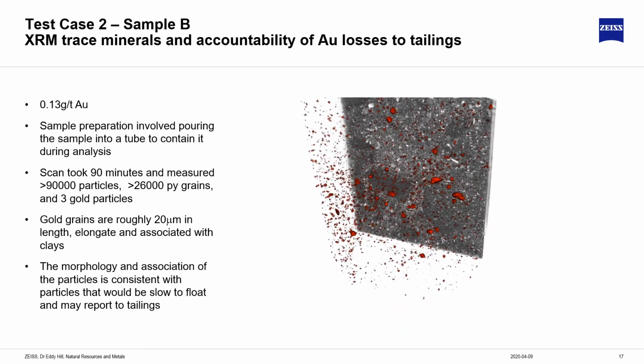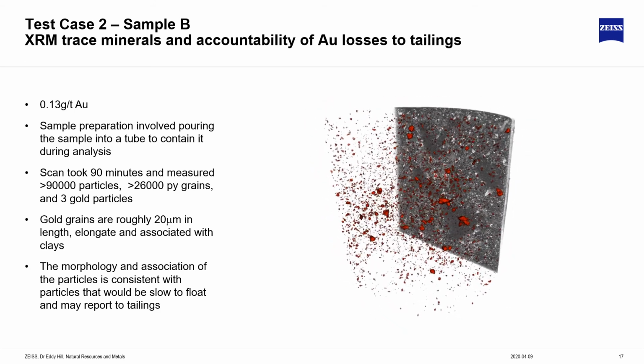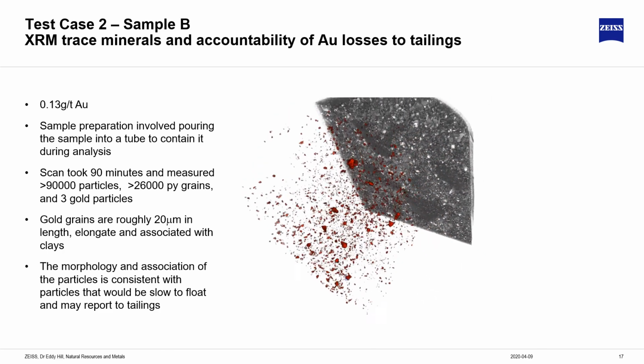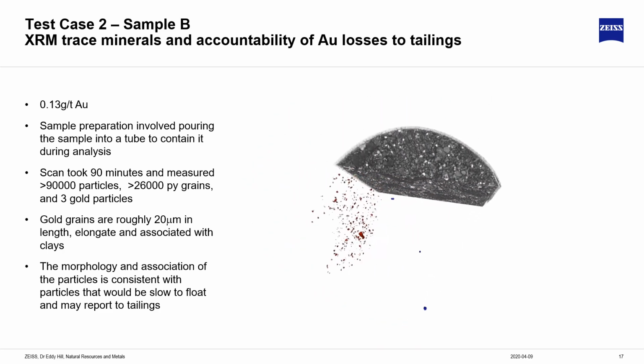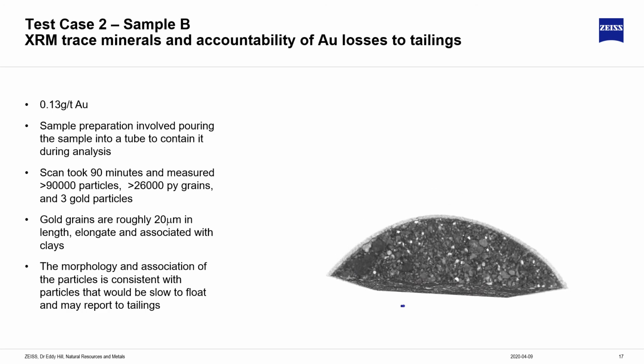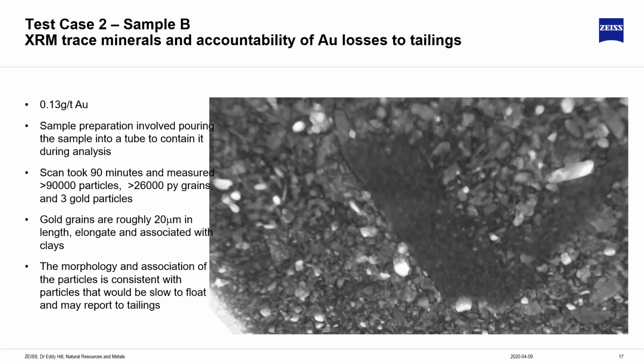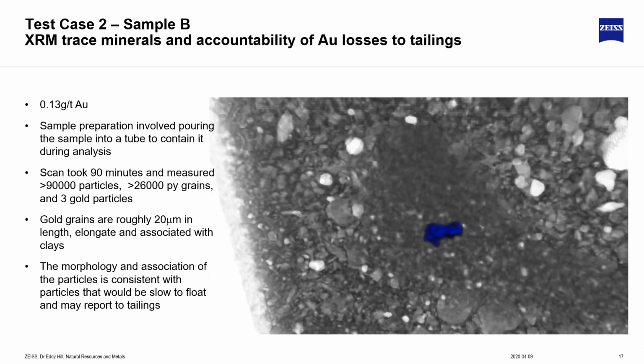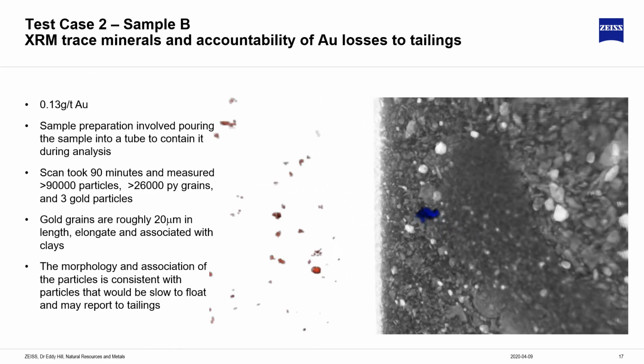And we see here a scan through the 3-dimensional volume of the sample, and the red particles are pyrite, and when we remove them, we're left with the 3 gold grains that we found. There we see the cigar shape of these particles.